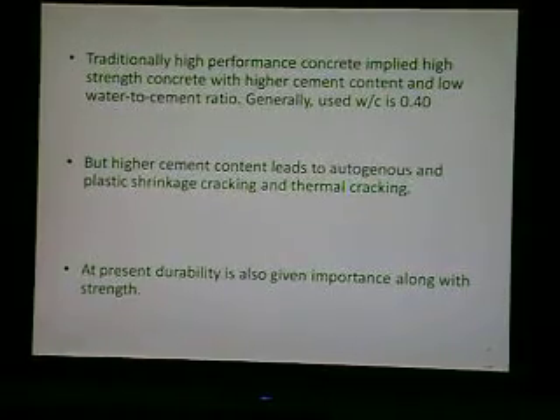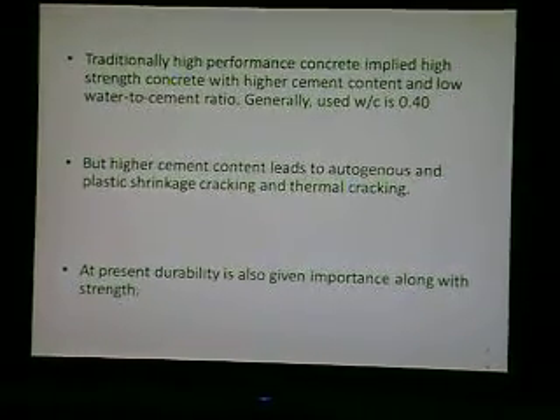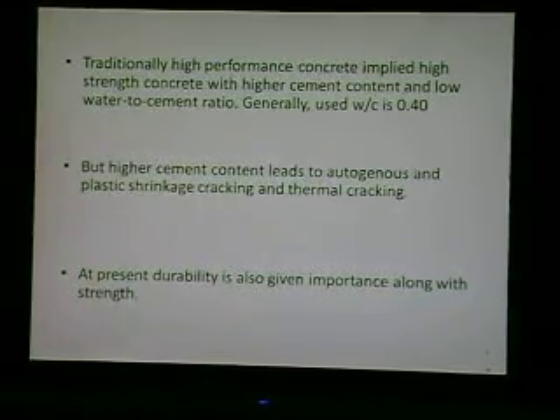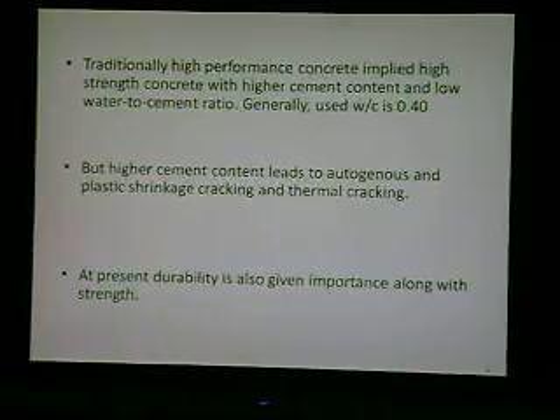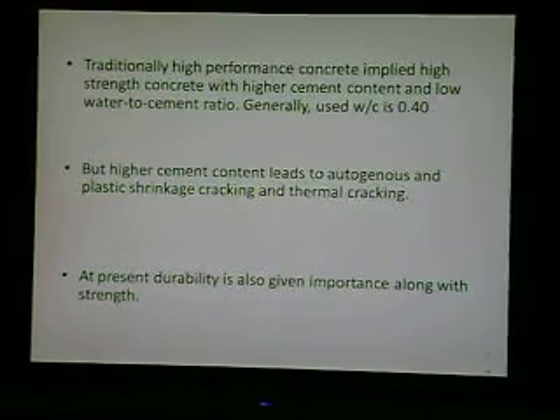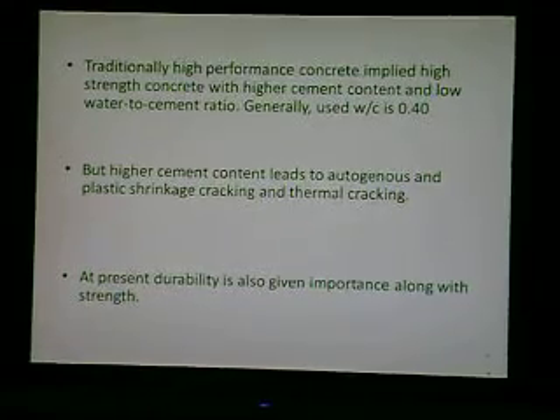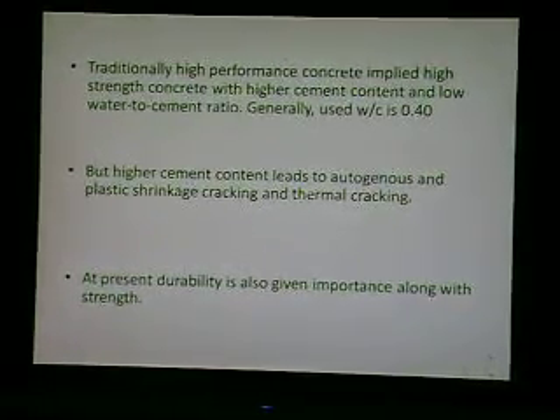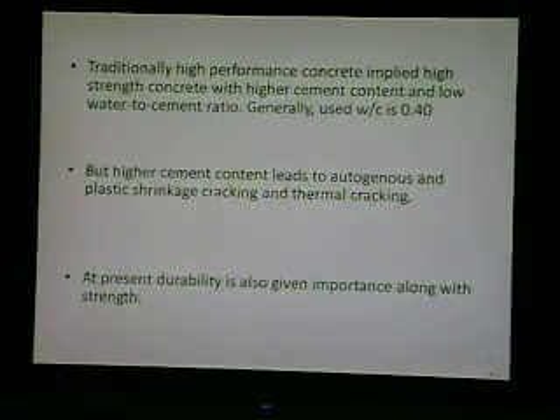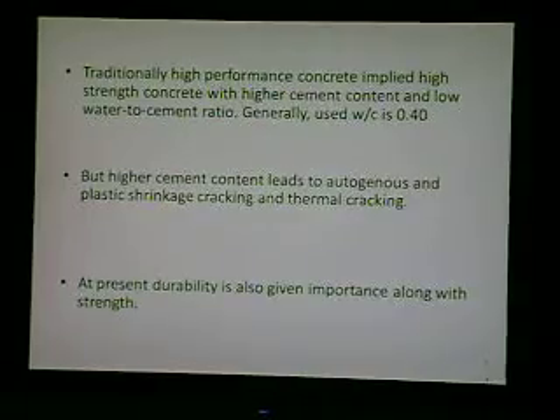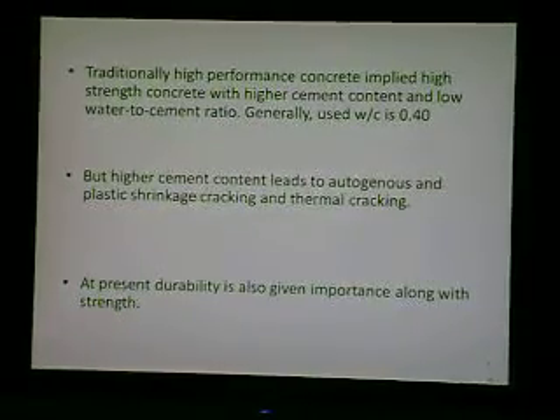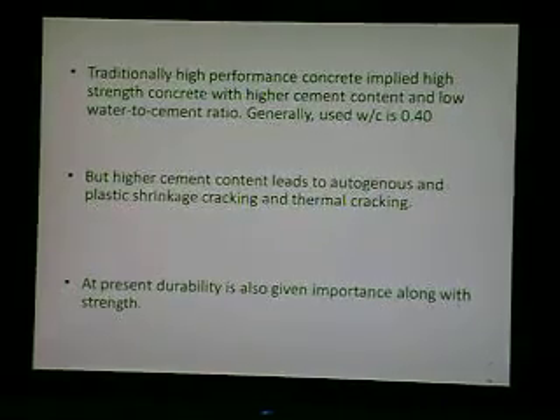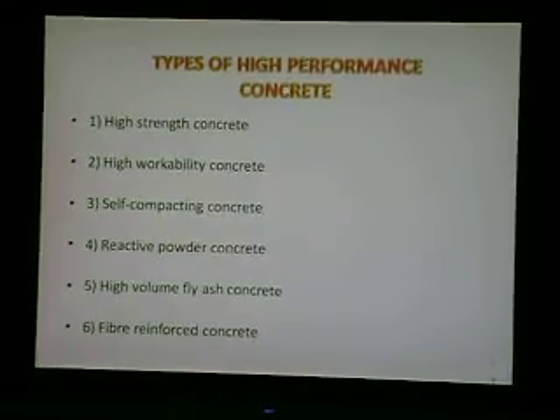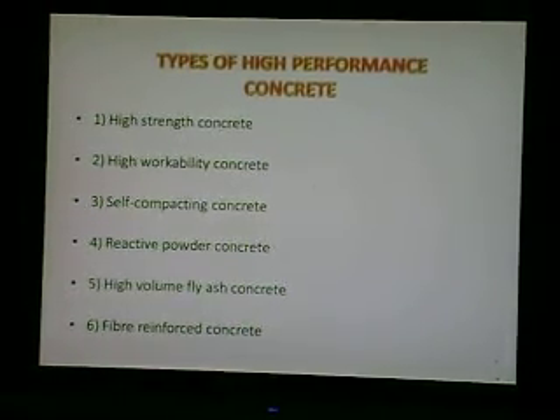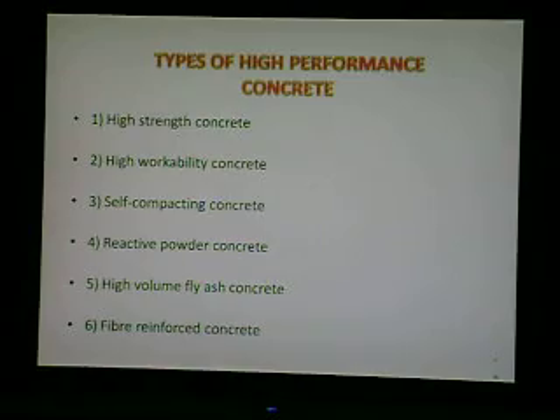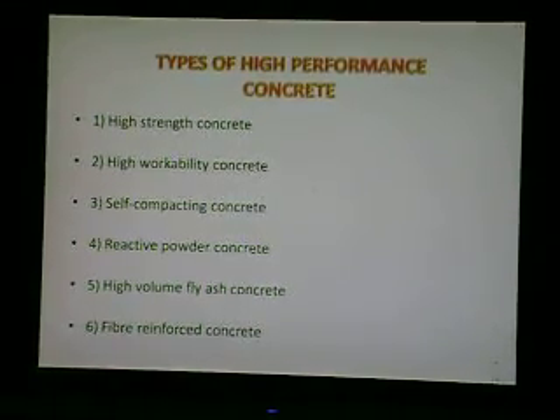Traditionally, high performance concrete implied high strength concrete with higher cement content and low water to cement ratio. But higher cement content leads to autogenous and plastic shrinkage, cracking and thermal cracking. At present, durability is also given importance along with strength. Types of high performance concrete: high strength concrete, high workability concrete, self-compacting concrete, reactive powder concrete, high volume fly ash concrete, fiber reinforced concrete.